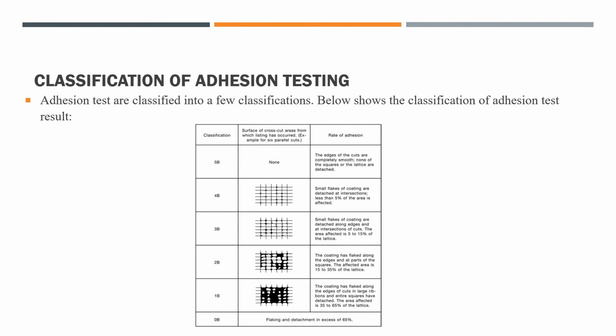Adhesion tests are classified into a few classifications. Below shows the classification of adhesion test results. The first one is 5B. At this rate of adhesion, the edges of the cuts are completely smooth. None of the squares of the lattice are detached. Then 4B, where small flakes of coating are detached at intersections. Less than 5% of the area is affected.